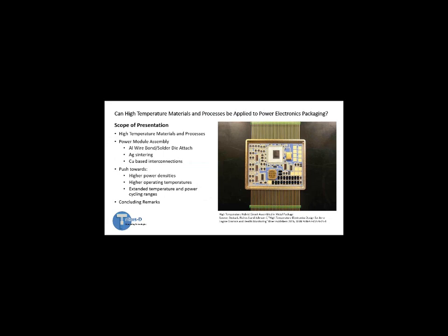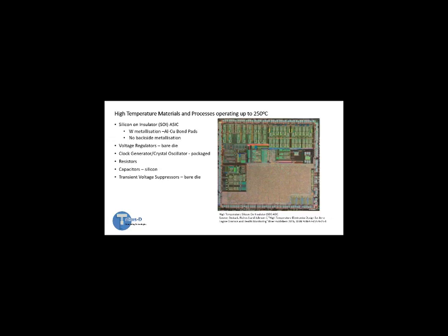That involved, one, developing specific electronic devices; two, looking at what was available on the market; and thirdly, asking how long the packaging would last. In the program, we developed an ASIC based on a silicon-on-insulator semiconductor technology, which has verified long-term performance at 225 degrees C, but could operate up to 250 degrees C. In some cases, we got it operating up to about 300 degrees C.